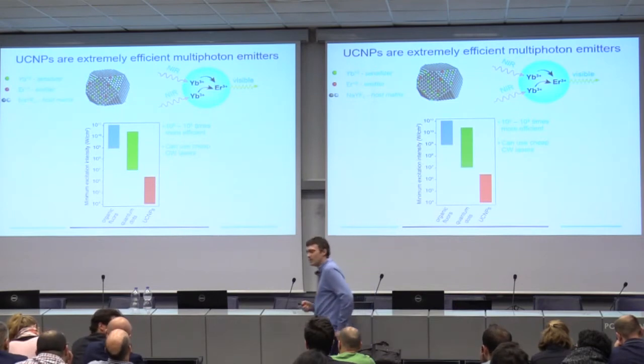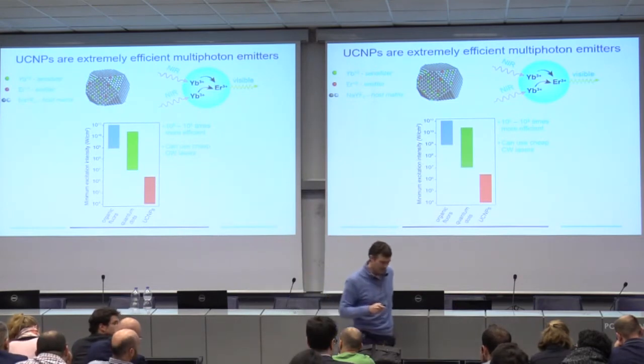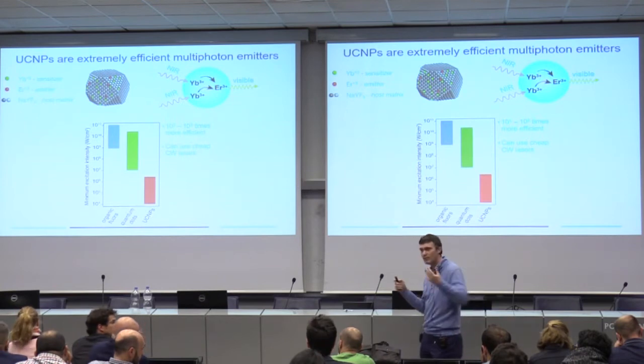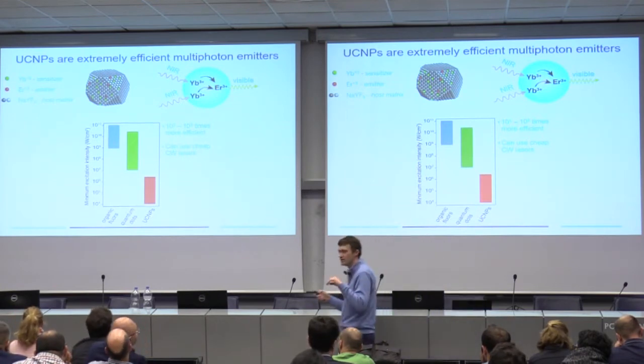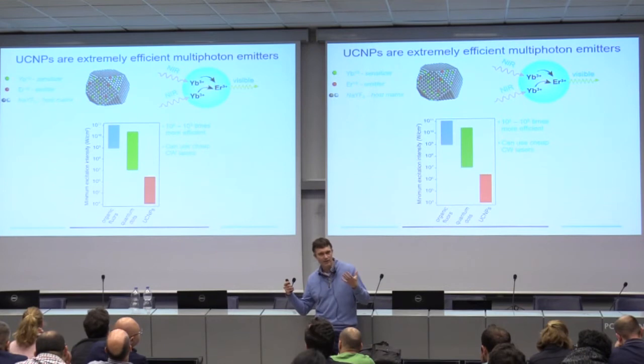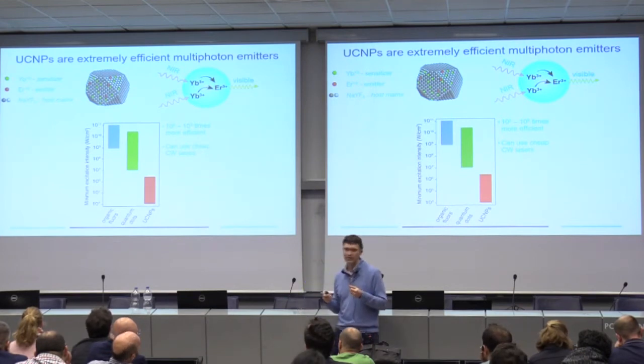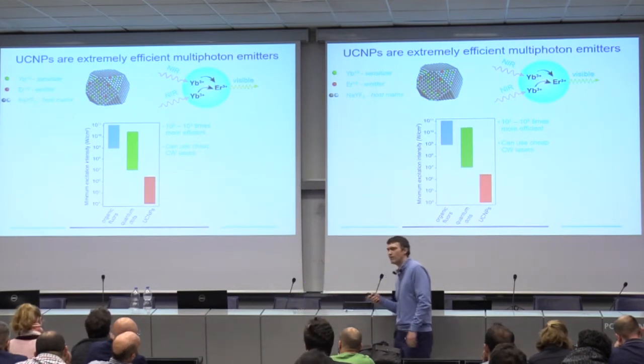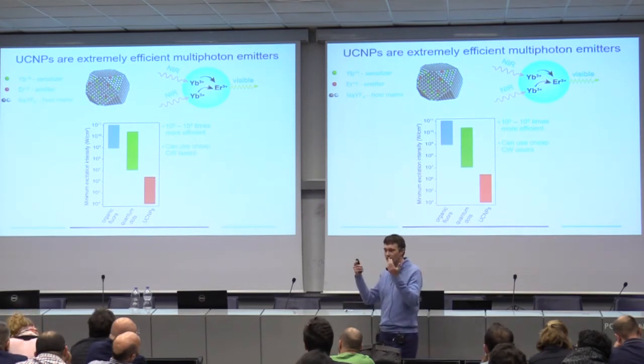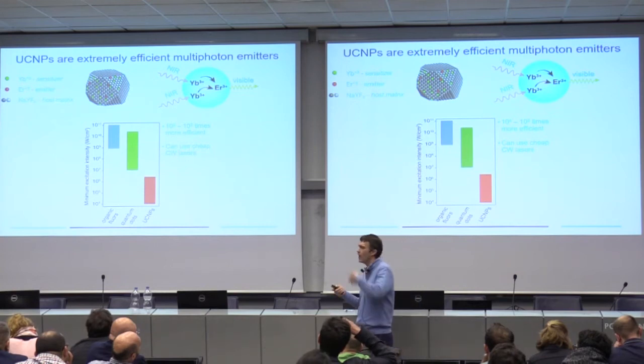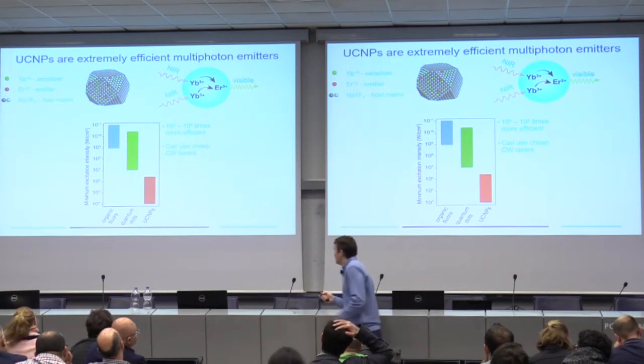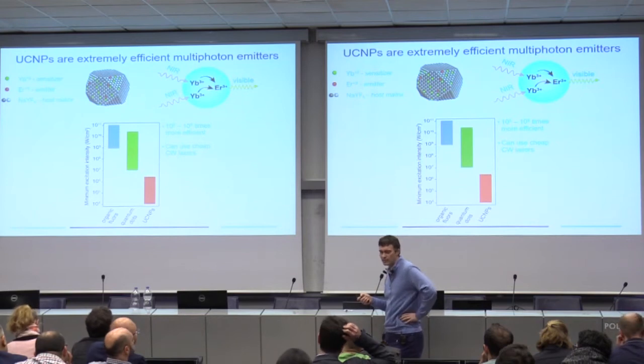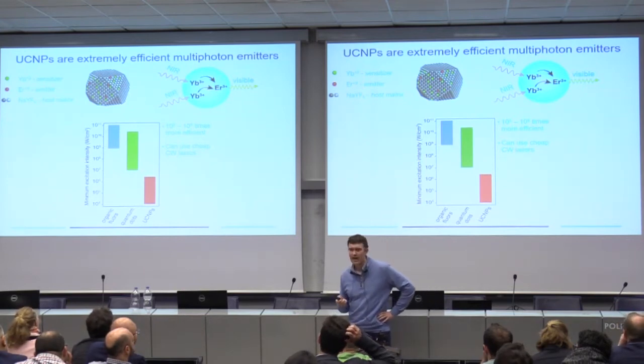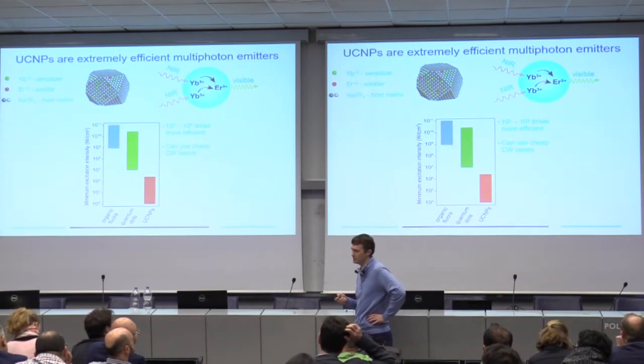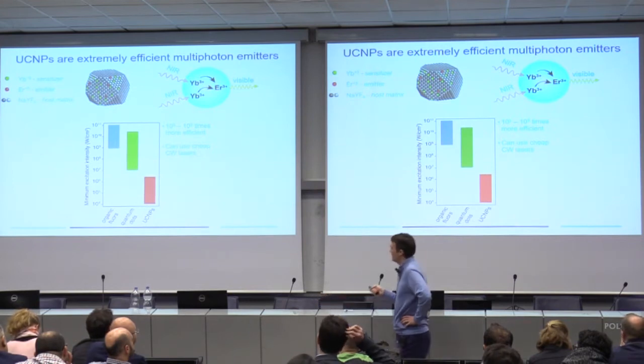Okay, so let me tell you, at least in a simple way, what these upconverters are. Upconverting nanoparticles are essentially ceramic or glass nanoparticles that are doped with lanthanide ions, rare earth ions. And they are very, very efficient at absorbing near-infrared photons and upconverting them so that they emit at visible or higher energy near-infrared wavelengths. To give you some perspective, they are about 5 to 8 orders of magnitude more efficient at upconversion than your best 2-photon dyes. And so that got people excited.